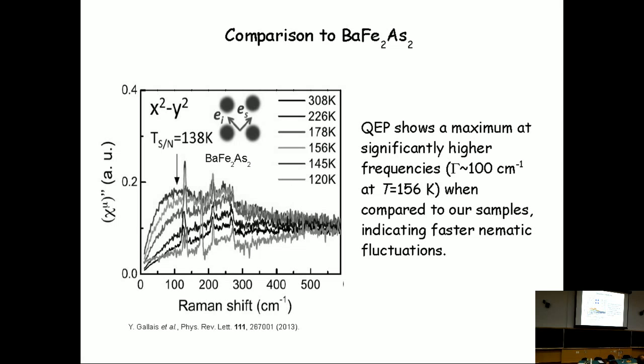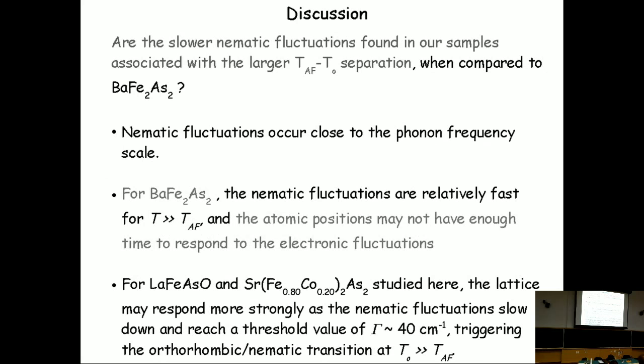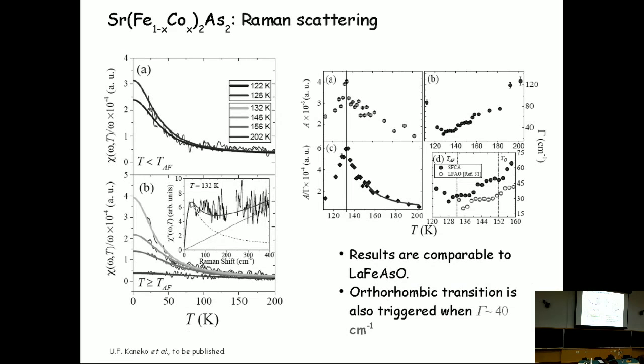But we didn't see the onset at the orthorhombic phase. We just saw one onset. You don't see any anomaly or any visible anomaly at like 150 something, which is the orthorhombic. Right, but they're too close. They're not too close. The reason why we started studying these materials is exactly because the other materials that have been studied before, the lightly doped materials, the difference was 1 Kelvin or less, and that was too close. And then we wanted to try a material where the separation is like 20 Kelvin, which is maybe not too close anymore.